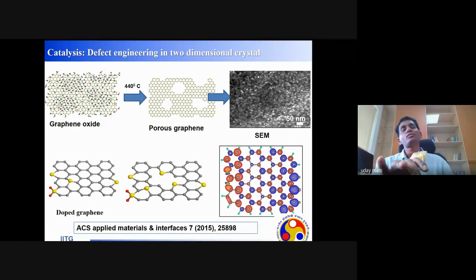These are the holes, and we can create very tiny holes. And once we create the holes, it is easy to dope with bigger heteroatoms. We have doped with sulfur, and those sulfurs are mostly incorporated near these pores, because we have confirmed from the XPS the configurations of these sulfurs. And we have also done density functional theory simulation. From that, we have found that due to this heteroatom doping, there is a redistribution of electrons and spin around some atoms around the edges. This redistribution, localization of electrons has some impact on the catalysis. We used it for oxygen reduction reaction catalysis. If you would like more detail, please go to this publication.